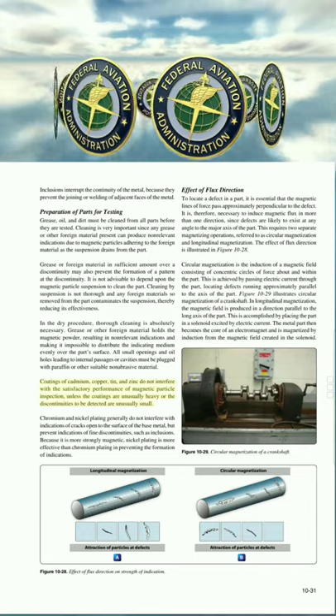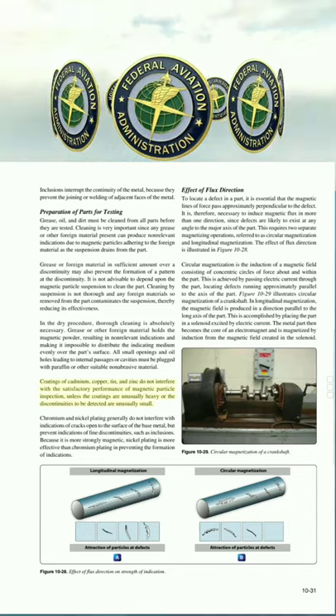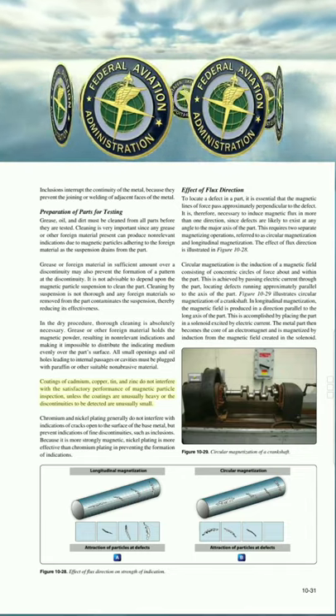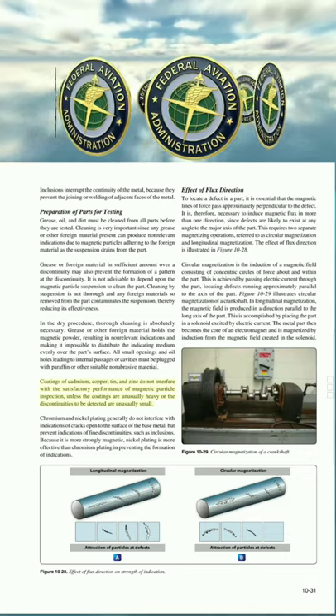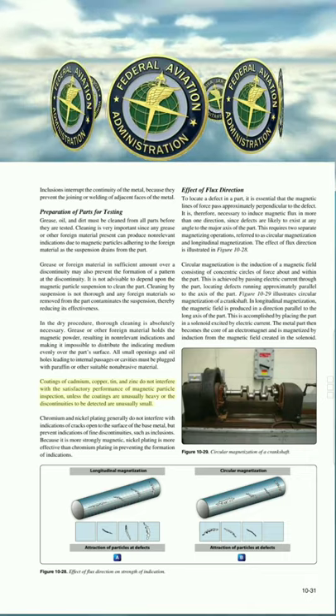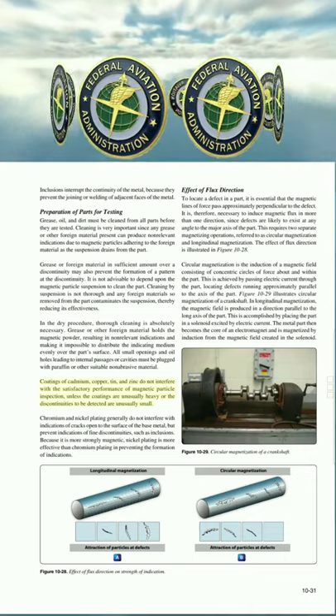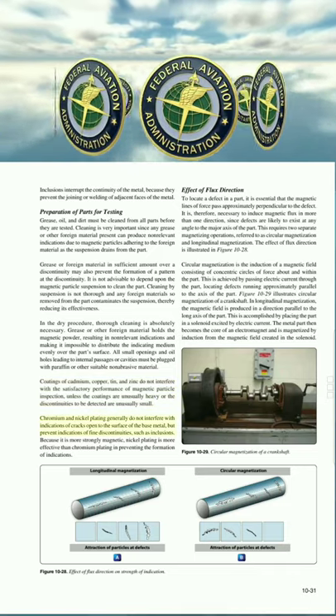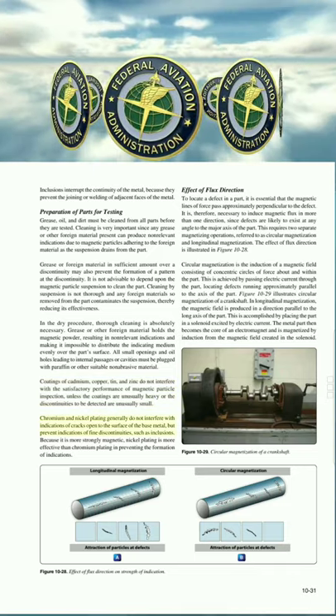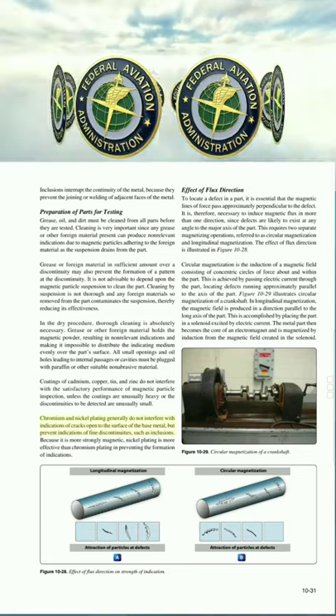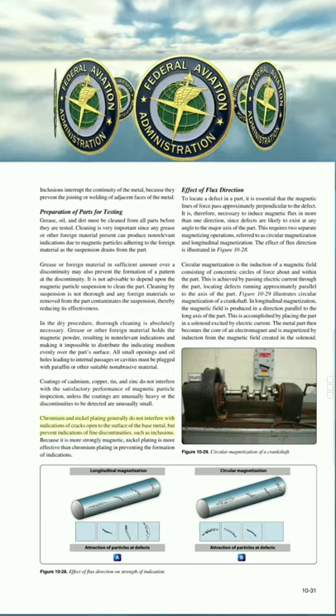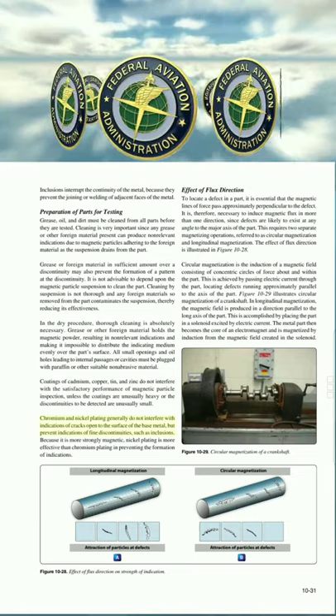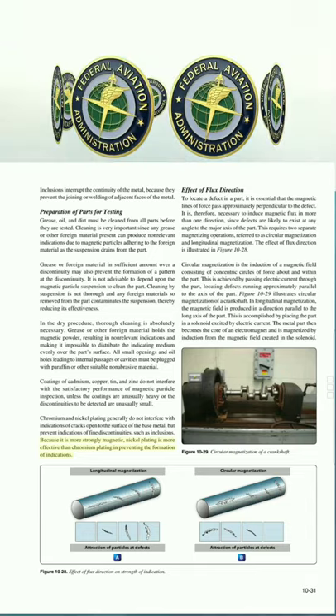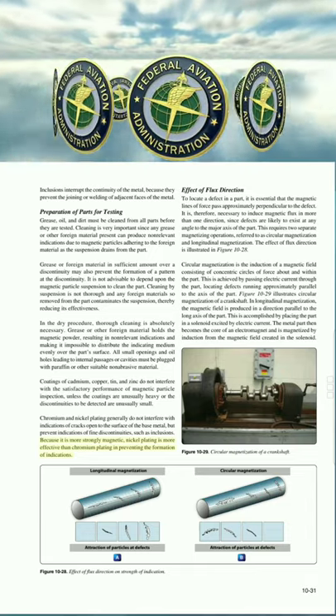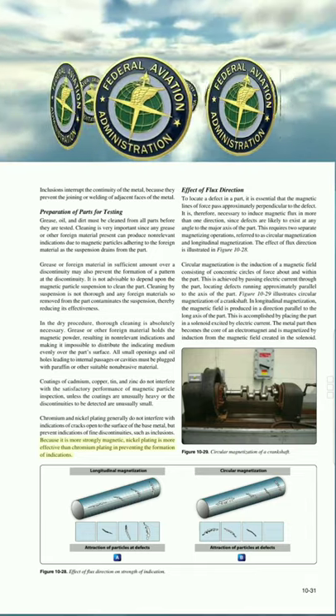Coatings of cadmium, copper, tin, and zinc do not interfere with the satisfactory performance of magnetic particle inspection, unless the coatings are unusually heavy or the discontinuities to be detected are unusually small. Chromium and nickel plating generally do not interfere with indications of cracks open to the surface of the base metal, but prevent indications of fine discontinuities, such as inclusions. Because it is more strongly magnetic, nickel plating is more effective than chromium plating in preventing the formation of indications.